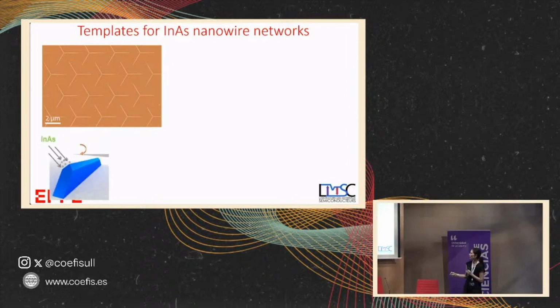So the idea we had is that we have the gallium arsenide, and then we change the atoms. We add indium and arsenic. And indium arsenide and gallium arsenide have a lattice constant that is very different. So indium arsenide doesn't want to grow on gallium arsenide, really doesn't want to, because it stretches it, and they don't want to be stretched. So if you try to put it on top, it will not go here on the oxide, because this is not sticking.